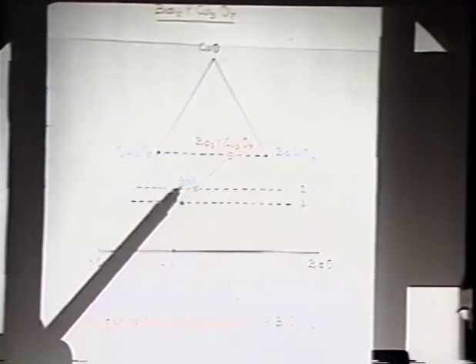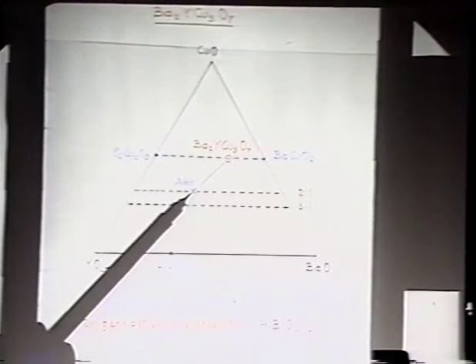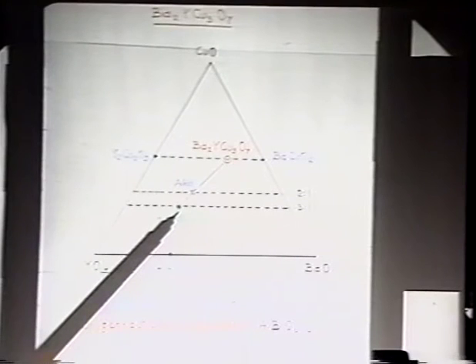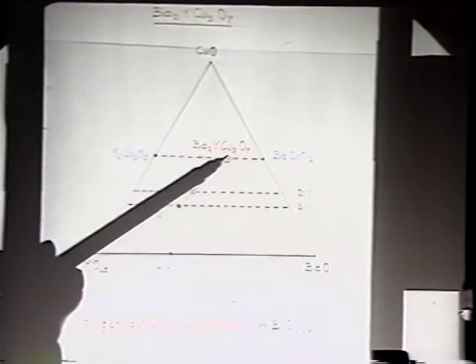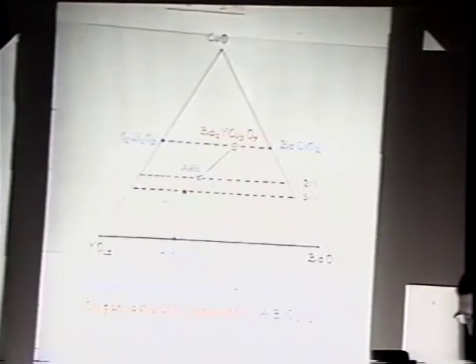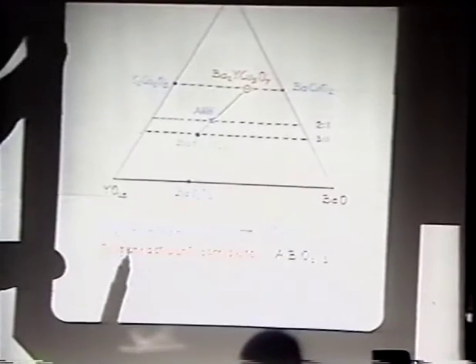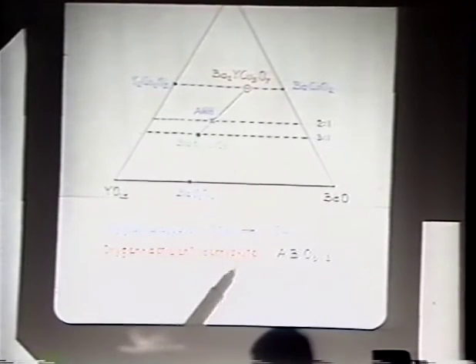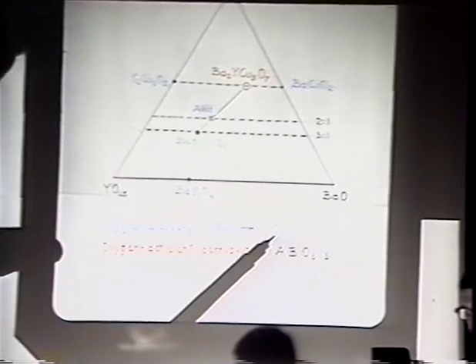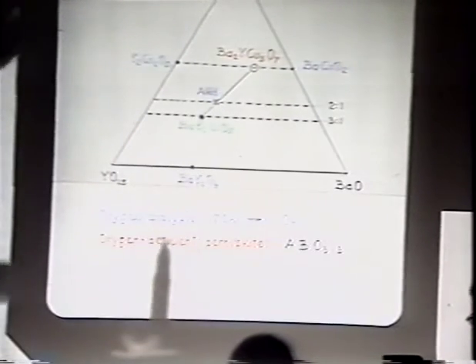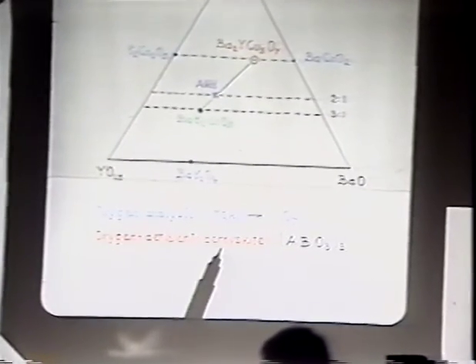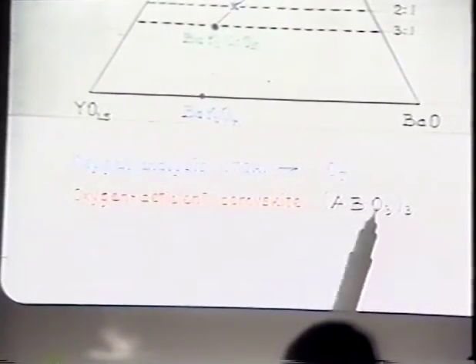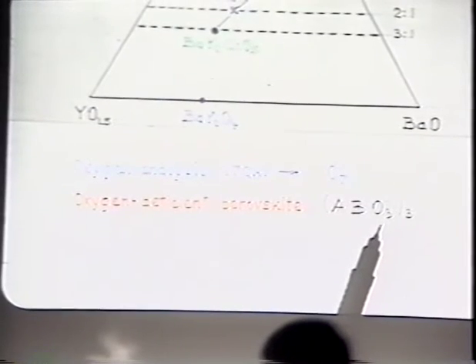So if one makes this composition, which is barium, yttrium-2, copper-3, as we just heard also before, we automatically get mainly, say, 2/3 of the green stuff and approximately 1/3 of the superconducting material. Through detailed oxygen analysis, we figured out that the oxygen concentration should be 7. So we can talk about essentially an oxygen-deficient perovskite, which generally would be written as ABO3 times 3. However, we don't have 9 oxygens there, we rather have 7 oxygens.